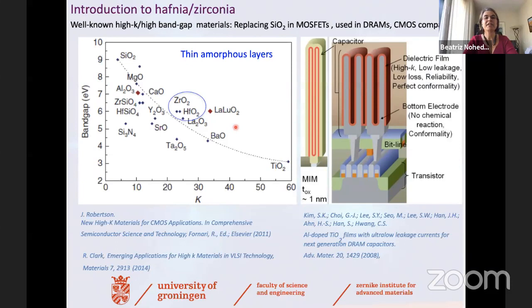So let me first go and introduce a little bit about hafnia and zirconia, which is actually very similar to hafnia. Zirconia and hafnia have not only the same valence, but also the same ionic radius. So crystals of hafnia and zirconia have very similar unit cell volumes, and they look very similar in many aspects. And they are very well known in the semiconductor field because they have been used as a substitution of silicon oxide as gate oxides and insulators. And you can see here in this diagram, band gap versus dielectric permittivity, that zirconia and hafnia are located in a very nice position, relatively large band gap and relatively large dielectric permittivity. That's why they have been preferred in many applications.